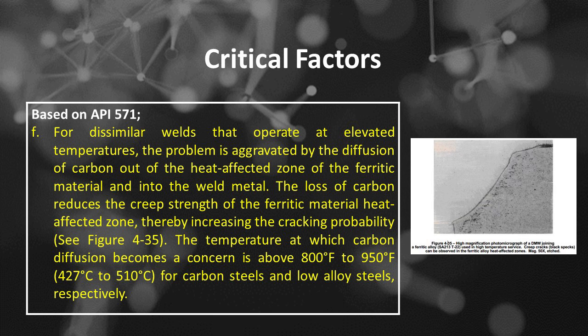The temperature at which carbon diffusion becomes a concern is above 800 degrees Fahrenheit to 950 degrees Fahrenheit, or 427 degrees Celsius to 510 degrees Celsius, for carbon steels and low alloy steels, respectively. See Figure 4:35, high magnification photomicrograph of a dissimilar metal weld, or DMW, joining a ferritic alloy, SA213T22, used in high temperature service. Creep cracks, or black specks, can be observed in the ferritic alloy heat-affected zones.